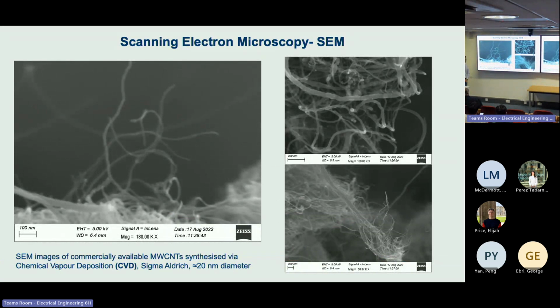So we did some SEM on the products we have and also the commercially available carbon nanotubes. So these are the SEM images of the carbon nanotubes produced by CVD. We purchased them from Sigma Aldrich. The diameter of the carbon nanotubes is around 20 nanometers. We can see the fiber is quite long and it's quite uniform.